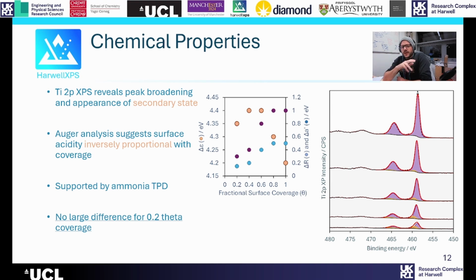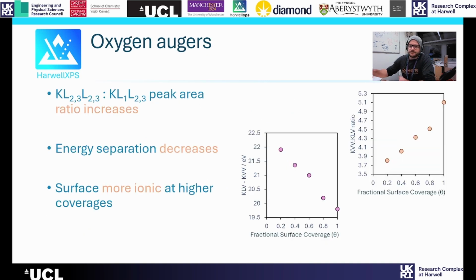But when we look at the chemistry by the XPS, it doesn't really show an outlier, it shows a general trend, so perhaps there is more going on than just this. These observations by the Auger parameter were further supported by linear combination fitting of the oxygen KLL in order to segregate the titanium oxygen and silicon oxygen contributions to this. When we looked at the ratio of the KL23L23 to KL1L23 Augers and the energy separation between them, both of these indicated a more ionic character for the oxygen as we approached higher coverages, which again is consistent with a decreased acidity.